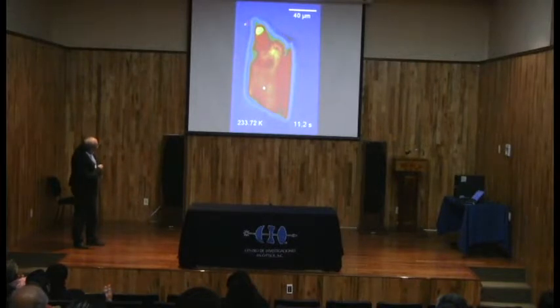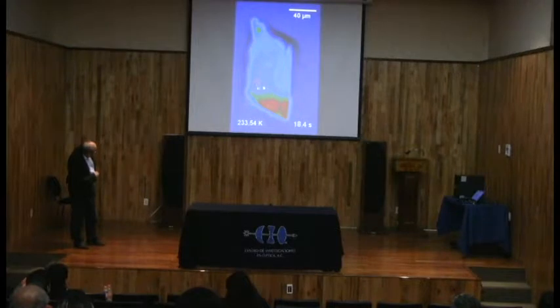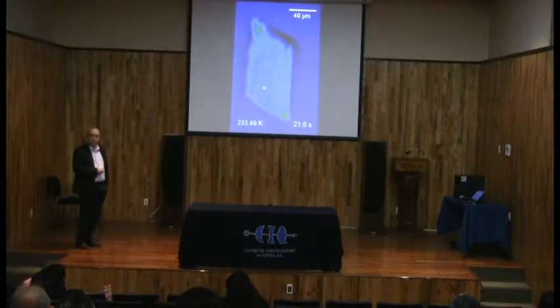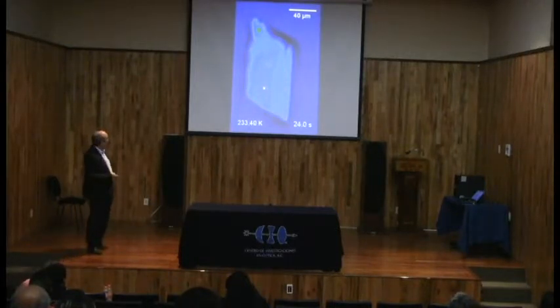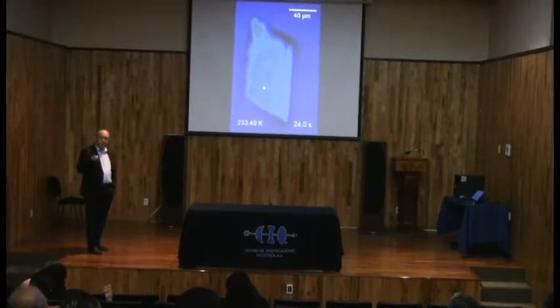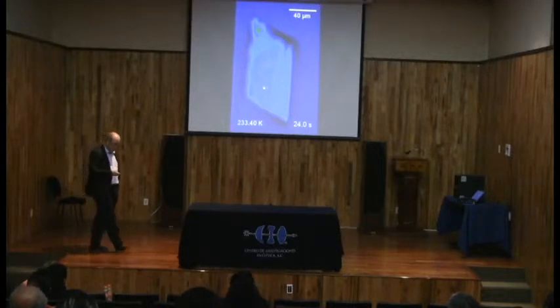You see, this system is in low spin form here. When the temperature increases, you see the system is switched by a process of nucleation and growth. And what we wanted to see is whether any defects we can generate on the crystal have an effect on the nucleation, on the growth, on the propagation of the spin state in the system.